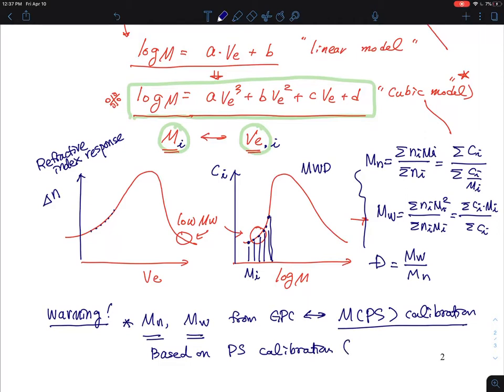And even, you want to say, what is lowest to the, what is highest calibration that you use to make this characterization, because this is all relative technique, so this molecular weight is not absolute molecular weight, but it is a molecular weight that corresponding to the one have essentially the same retention, elution time or retention time and behavior, and that is related to the size. So we are just talking about the molecular weight that you calculated from the measure, from the GPC, is not an absolute molecular weight, so that's one of the limitations.